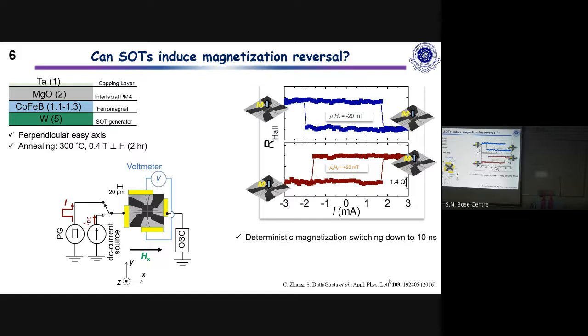And this experiment was done with a DC current. If we apply an electrical pulse, we showed that we can reproducibly switch it down to 10 nanoseconds. So this means that the spin-orbit torques definitely can switch the magnetization of a heavy metal ferromagnet joint. But the question is that, as you can see here, we need to have an applied in-plane field in order to have deterministic switching. So the question is, why do we need this in-plane field? And the problem is, can we actually eliminate the requirement? Because this is not practical from the point of view of device application.